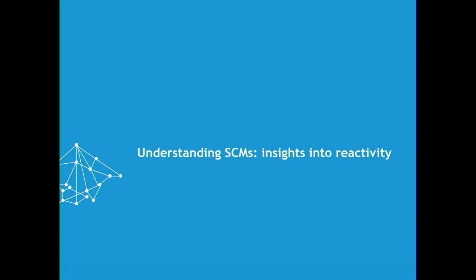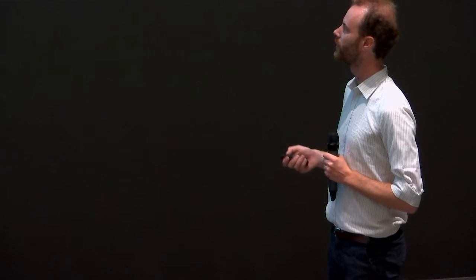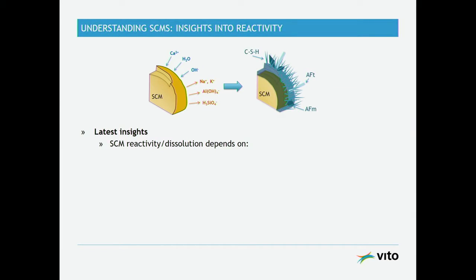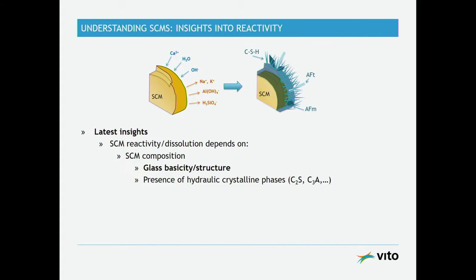Okay, maybe now a bit more about taking a step back and looking into model systems. Well, as we see SCMs, they actually react through the solution and produce calcium silicate hydrates and typical reaction products in combination with cements. The reactivity or the dissolution rate of these materials are known to depend on the composition of the SCM, for instance, the structure of the glasses, the basicity of the glass, the presence of hydraulic crystalline phases as well, and also the pore solution composition.